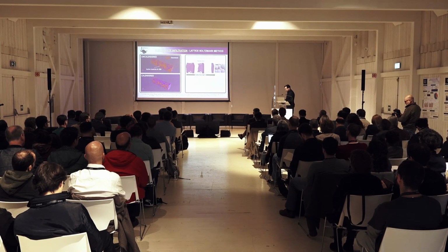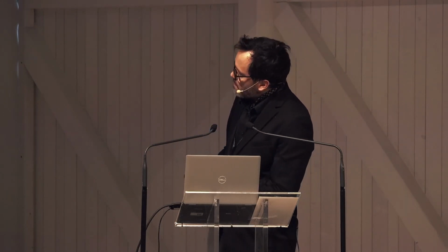Well, the model is capable of predicting where exactly the air will remain trapped, right? To then provide some insights maybe on how to avoid this problem. And here you see an example of simulations. These are 3D simulations, but here I'm showing in 2D how the electrolyte infiltration looks in cell sandwiches, where you have anode, cathode, and separator. Separator is a polymeric membrane with some porosity. You see that this process is highly heterogeneous, okay?